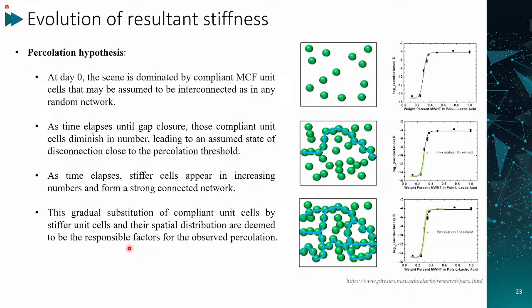When we look at these curves, it reminds us of the percolation hypothesis in physics. So we can interpret the results from this perspective. At day 0, the scene is dominated by compliant MCF unit cells that may be assumed to be interconnected in a random network. So as time elapses until gap closure, those compliant unit cells diminish in numbers, leading us to assume the state of disconnection is close to the percolation threshold. As time elapses, stiffer cells appear in increasing numbers and form a strongly connected network. So this gradual substitution of compliant unit cells by stiffer unit cells and their spatial distribution are deemed to be the responsible factors for the observed percolation phenomena.